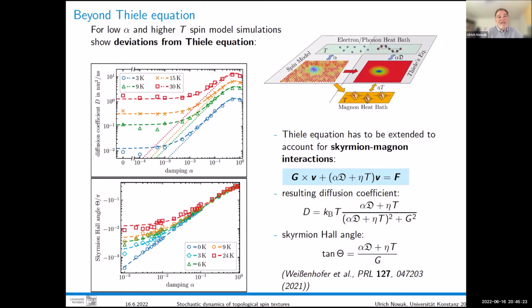So when you go to the quasi-particle equation of motion, the Thiele equation, you assume that you kind of average your spin model and assume a rigid form shape of the skyrmion. In the original spin model, you had a heat bath. And with this damping constant alpha, you were coupled to the electronic or phononic degrees of freedom, let's say, of your material, okay? In the Thiele equation, that becomes this alpha D. But there is now another heat bath, and that's the point. There's another heat bath, namely, the skyrmion also interacts with the magnons.